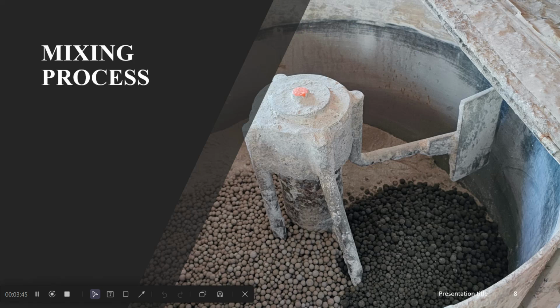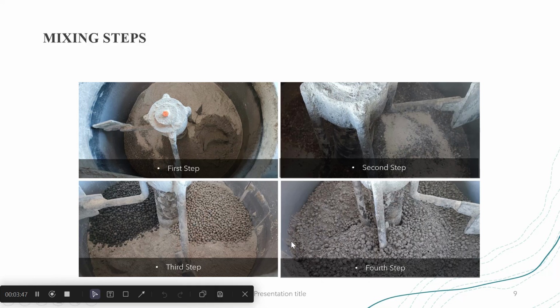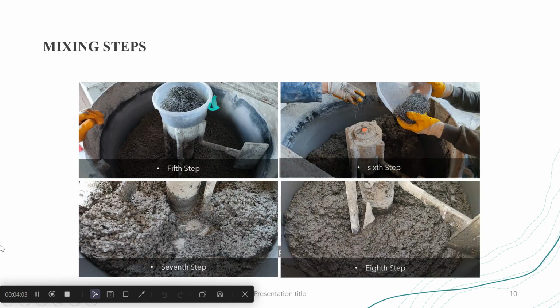This is the mixing process. We started with the first step, adding the sand and fly ash, and in the second step we mix it. In the third and fourth steps we added the aggregates of slag and mixed it. In the next steps we added the steel fiber and the sodium silicate, as you can see in the picture.